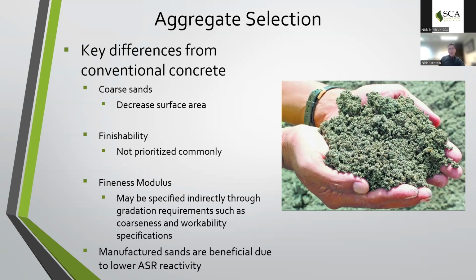When it comes to actual sand performance, we tend to see and use coarser sands. Manufactured sands tend to achieve this result for us and also help benefit with low ASR reactivity. And so we've tried to incorporate more and more manufactured sand into the creation of our high performance mix designs when available to help assuage any sort of ASR concerns, even though they generally are covered regardless through the higher levels of SCMs utilized for these types of mix designs.